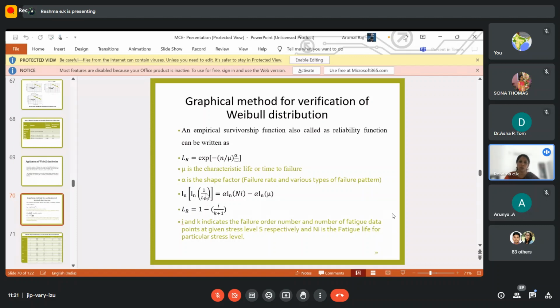When I take one logarithm here, that means to linearize the data. And when I take the double log, that is to get a probability model. That is why there is a double log; there is a reason behind everything. When you do something, you might just follow the procedure, do everything and finish it off. But you should learn why we go for it. See the last formula, the double logarithm is there. I could just use this double logarithm formula and complete my work, but it's better to have a good hold on why we are using it and how it came.